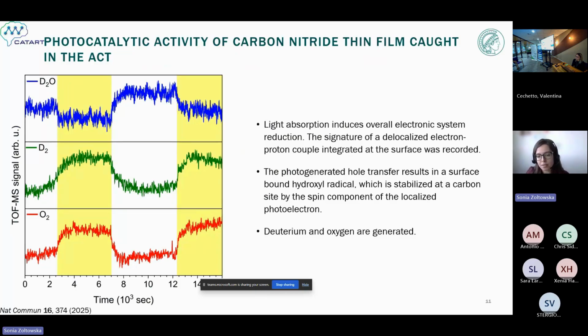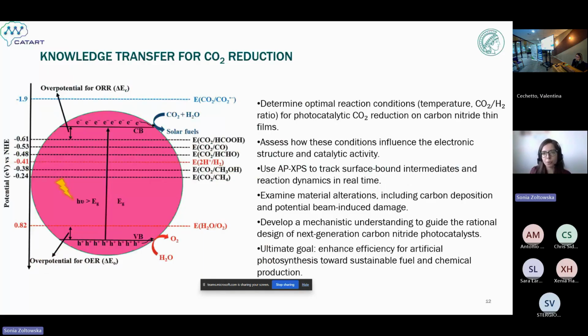And after all those results, we were asking ourselves how we can now use the same catalyst, so again the carbon nitride film on the gold substrate, and use this knowledge to transfer it and try to make CO2 reduction, which is a key reaction in our project. So in general, we started from the information about CO2 reduction which we already have. We know that the process requires several steps: absorption of light, charge separation, then the diffusion of the charge to the surface, and finally the reaction.